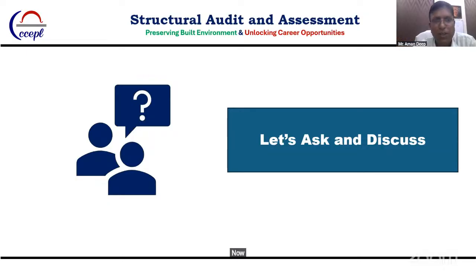Now your question is what should be done? Till now I have just analyzed the situation. Now what should be the appropriate measure to come out of this situation? For that you would have to check at some locations whether the corrosion has already started, or it is at a nascent stage, a stage 1 of corrosion, or the corrosion is very deeply spreading inside the building. Though the probability is showing 90%, it means that there should already be a good level of corrosion at many locations.